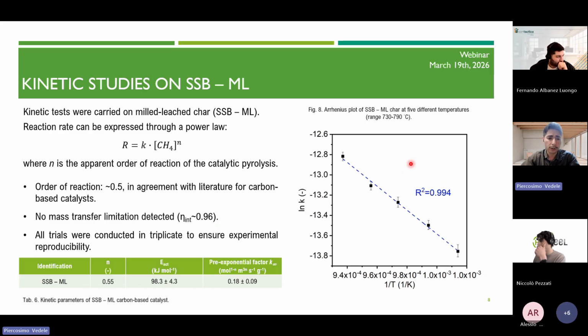From each temperature, we were able to obtain a kinetic constant, and through the Arrhenius plot, we can get the order of reaction, the activation energy, and the pre-exponential factor. The order of reaction is close to 0.5, in agreement with that of literature typical of carbon-based catalysts, and also the activation energy is mainly related to the defect-driven mechanism typical of carbon-based catalysts. All the tests were conducted in triplicate to ensure the reproducibility of the tests.